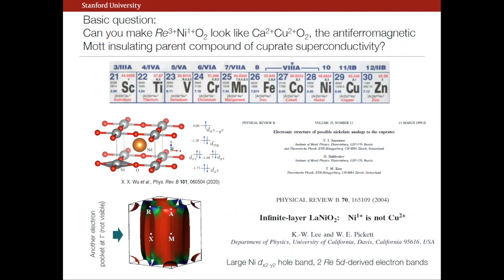nickel group. And so there's a little bit more heterogeneity as far as I understand in what happens, say, in LDA plus U or various attempts to deal with correlations. But qualitatively, again, the kind of consensus notion is this x squared minus y squared band will gap out into an upper and lower Hubbard band. And what's left then, to varying degrees, is an electron pocket, again, of this hybrid character.